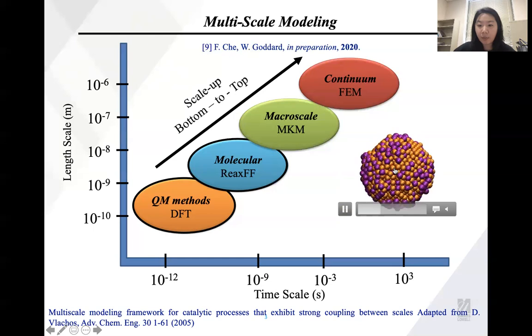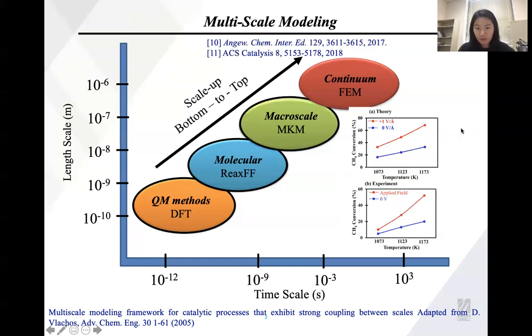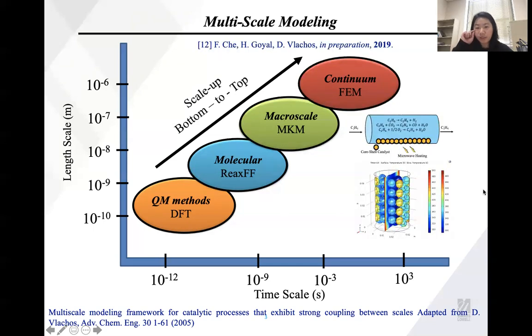We can even scale up to the microscale, mainly using mean-field microkinetic models, and we can do a direct quantitative comparison between the experiment and the theory. What is the yield? What is the selectivity of certain reactions? We can go up to continuum transport models, to see the mass transfer and heat transfer, approximated by the finite element method. This is extremely important when your reaction has non-uniform temperature, or non-uniform pH in the electrochemical cell. So this is an overview of the multi-scale simulation.